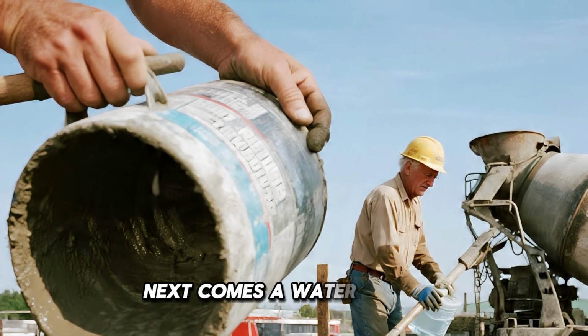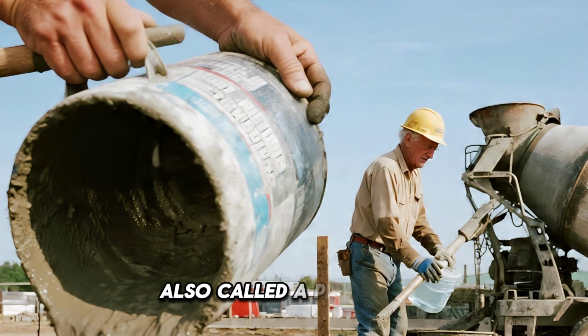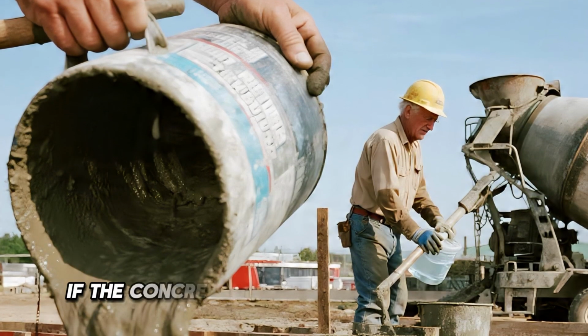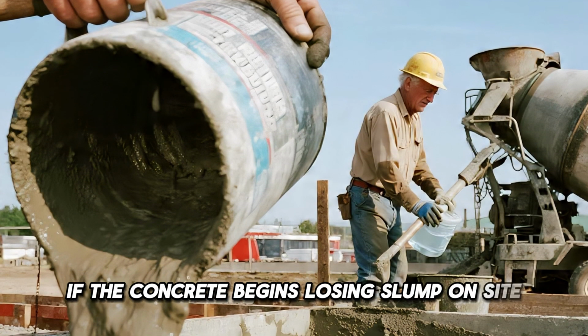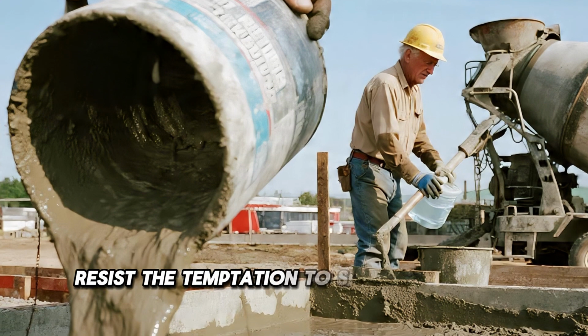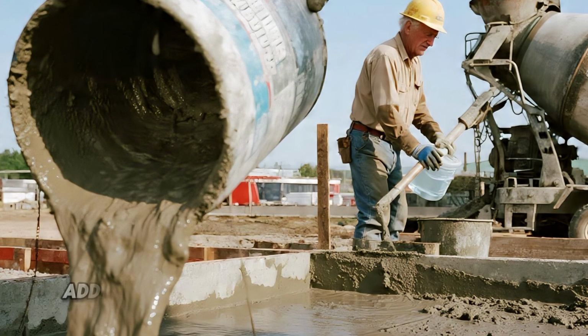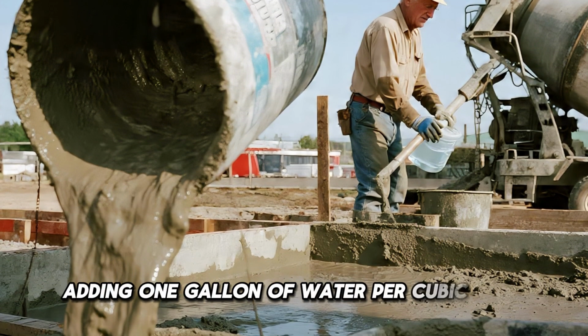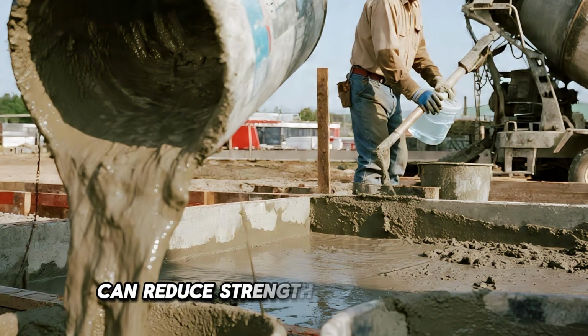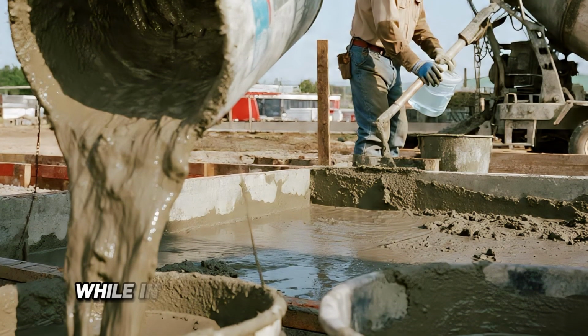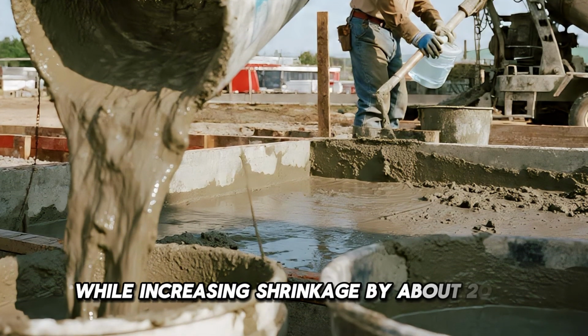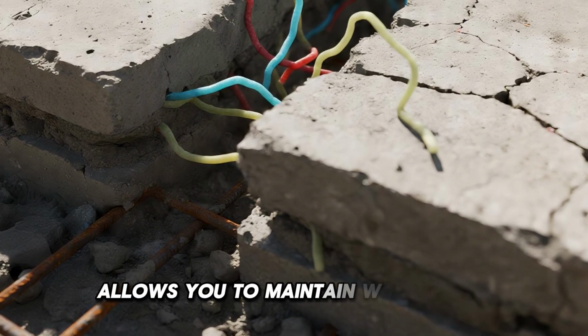Next comes a water reducer, also called a plasticizer. If the concrete begins losing slump on site, resist the temptation to simply add more water. Adding 1 gallon of water per cubic yard can reduce strength by roughly 10%, while increasing shrinkage by about 20%. A water-reducing admixture allows you to maintain workability without paying that price.